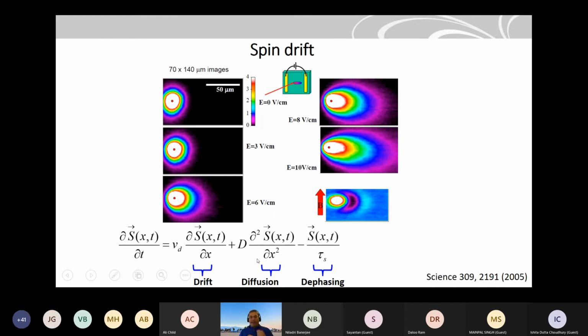Now add another parameter. Let's say add an electric field. So you have a semiconductor, you apply this voltage, and you are doing the same experiment. So you create spins, and this is for 0 voltage. This is for 3 volt, 6 volt. This is 8 volt, and this is 10 volt. So what you see here is that you create spin polarization, and with electric field, you actually drift this spin polarization. So the spin is getting drifted with the electric field.